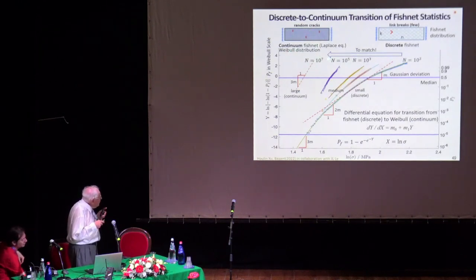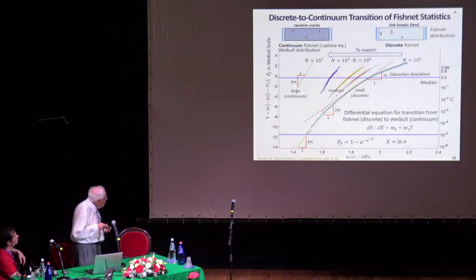And that we did not simulate. That's too much. But it must eventually go to the straight line. What is interesting, the straight line has a slope 3 times the Weibull modulus. It is much less scattered than here. The Weibull modulus is here, m. This goes to, actually can be seen as an envelope of several straight lines, transition mathematically. And this is 2m and the 3m. The 3m appears here. So I tried to match it. And we found a beautiful relationship, actually, 2 months ago.